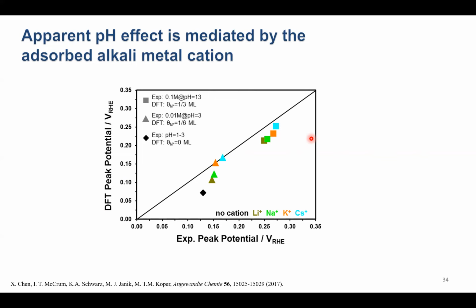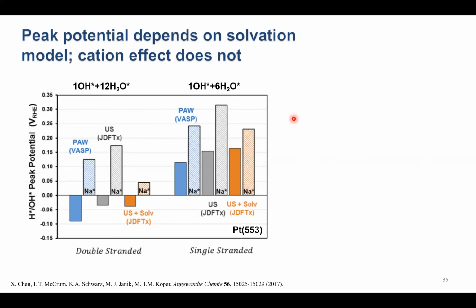I will mention something very important to consider here, which is that the absolute level of accuracy we see between DFT and experiment depends on a lot of things, right? If we used a different DFT exchange correlation functional, we'd get different potentials, and they would then fall maybe further or maybe closer to this y equals x line. Importantly, we can show it also depends on how we model solvation. And so I mentioned we've always used a small amount of explicit solvent. Here, what I'm showing is the DFT calculated step peak potential in the absence of sodium and in the presence of sodium for hydroxide adsorbed with a lot of explicit water and hydroxide adsorbed with less explicit water.